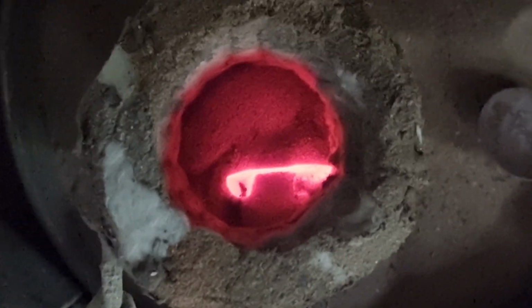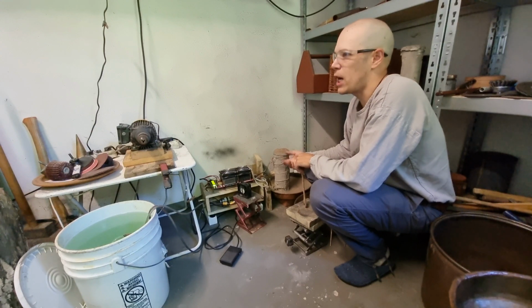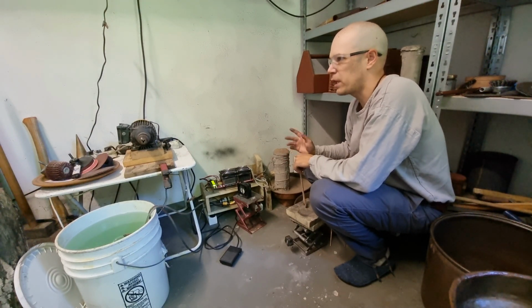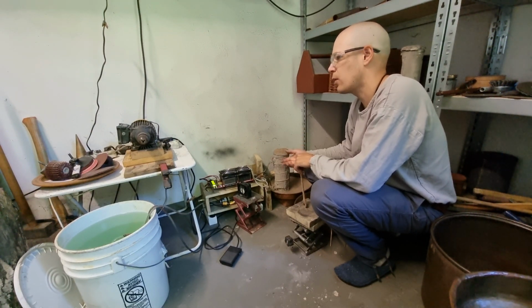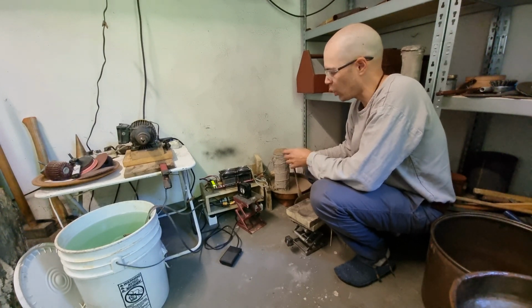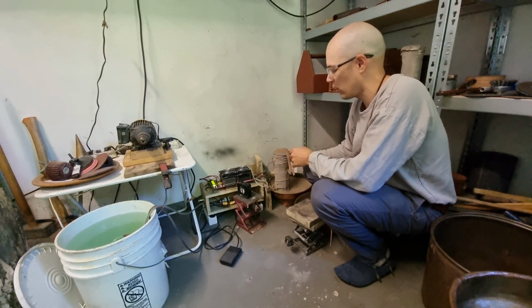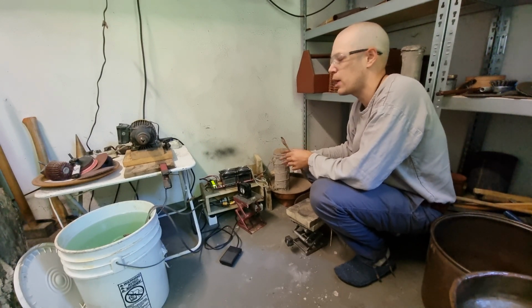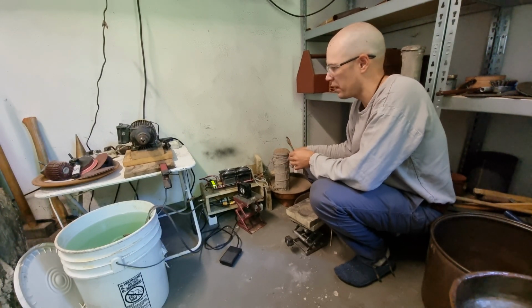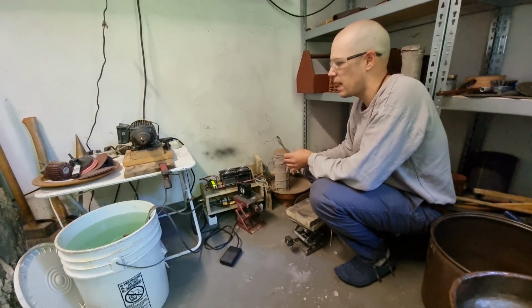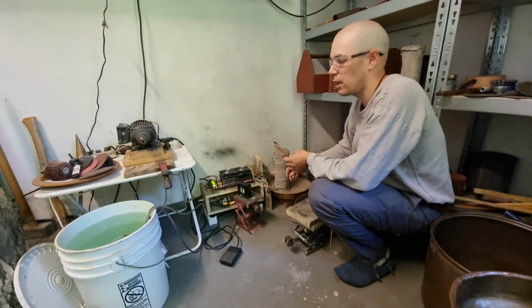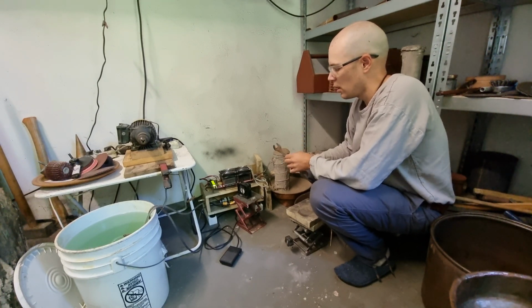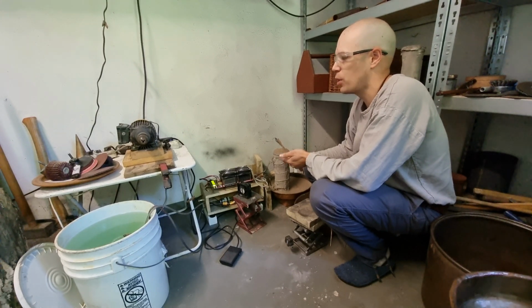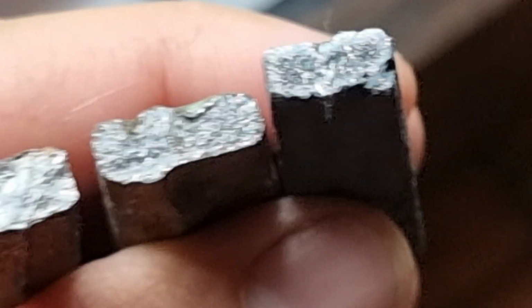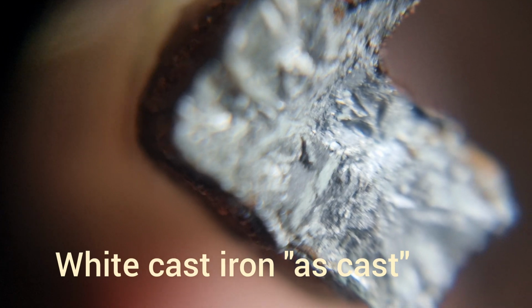And the induction heater heats iron up to about that Curie point, so that is about 750 or so centigrade. And beyond that, it gets harder and harder to heat iron by induction. So we reach about 800, 900 centigrade with all that insulation here, but not really far beyond that. So that is the sweet spot for decarbonization, because at that temperature, at about 950 centigrade, the iron carbides decompose. And so we got a separation of the carbon and the iron.